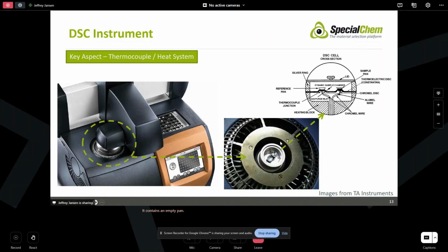We're going to talk more about pans later. So if we look at it here, we have our sample enclosed in this pan. Here we have that empty pan. And essentially what we're doing is measuring the heat or energy required to come into this system to keep our sample at the same temperature as our reference. For example, as we undergo a melting point, we have to pump more heat into that sample in order to melt the crystalline structure of the material, all while trying to increase the temperature within our sample to match that of the blank or the reference.